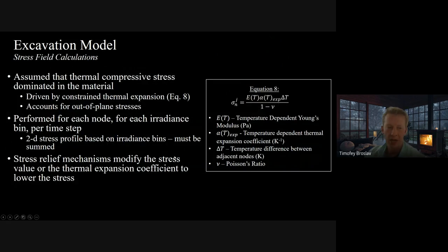And this is done per time step. And so you have a 2D stress profile based on the irradiance bins. Like I said, stress relief mechanisms were used to modify the stress value, or modify the thermal expansion coefficient to lower the stress as needed. For instance, if material began to melt, or there was some sort of stress relief going on.